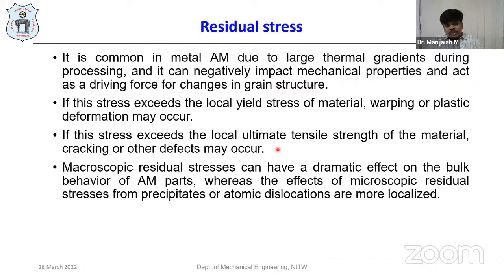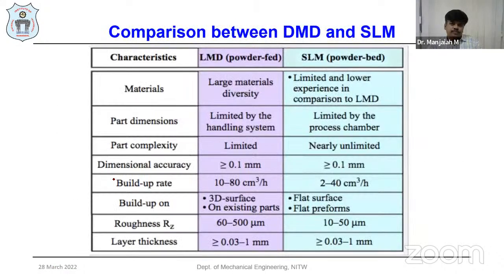Some macroscopic stresses have a dramatic effect on the bulk behavior of the materials. It means it will deform the shape of the components even after the fabrication. Some micro residual stresses occur in the precipitates, where atomic dislocations take place in the localized area. You see the macroscopic stresses, how they affect the printed component. These are all the defects. Deformation has taken place in this top surface, and all these kinds of defects are created because of the residual stresses.